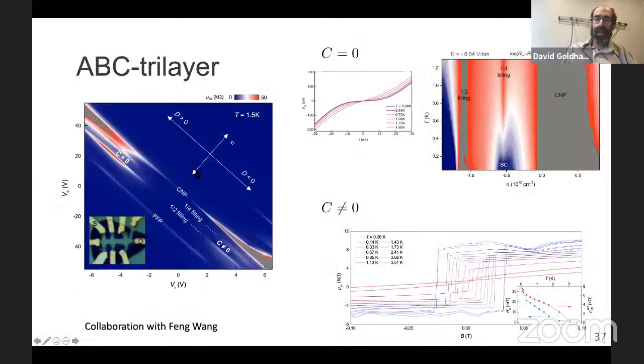So this is not the only orbital magnet system that's now been discovered in graphene-based systems. We collaborated with Feng Wang's group in studying ABC trilayer aligned with boron nitride, and they're in the valence band at 1/4 filling. So again, 1 hole per moiré cell. So maybe that has some important meaning. There's again a magnetic state depending on the direction of the out of plane fields.